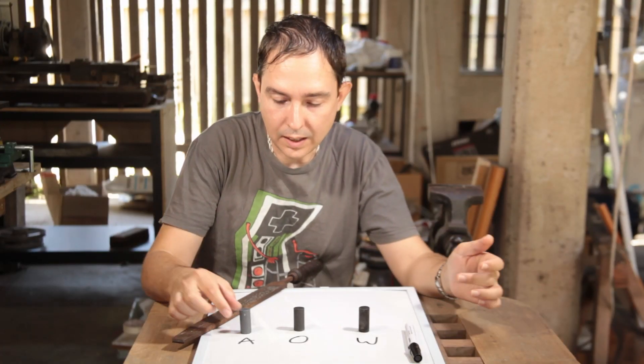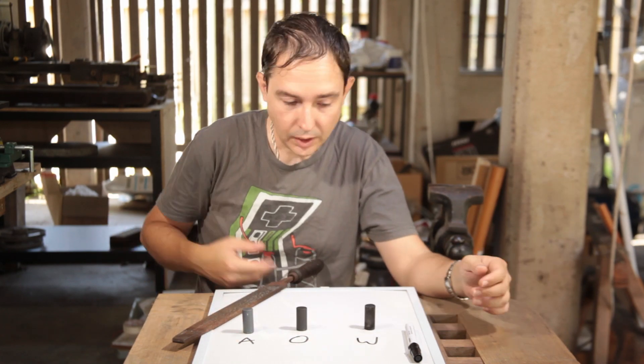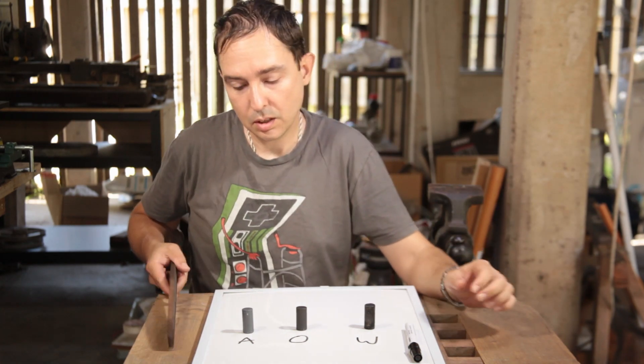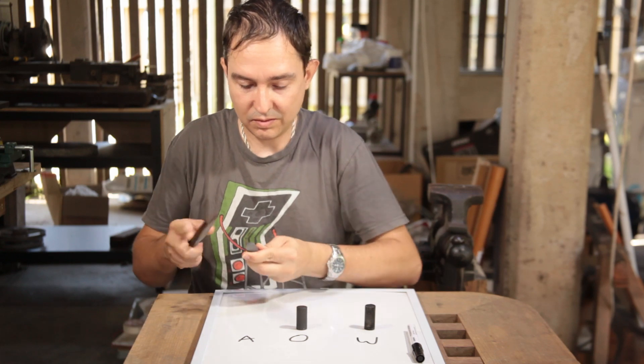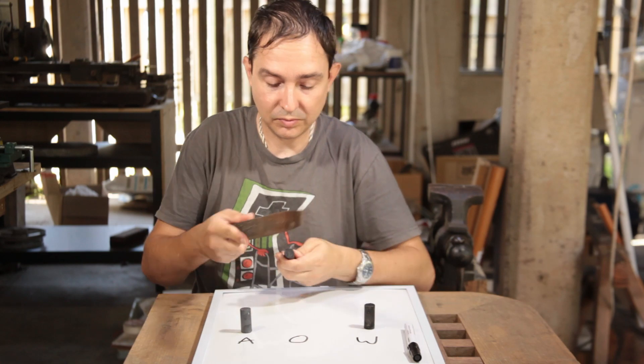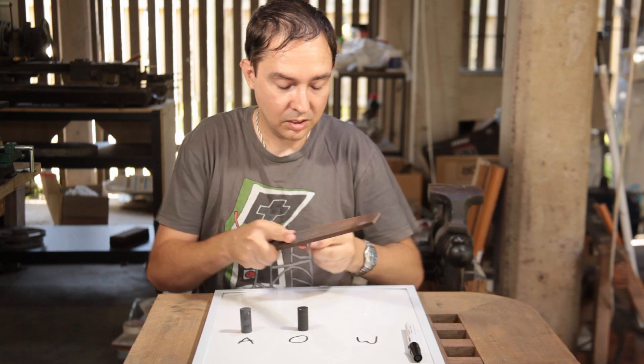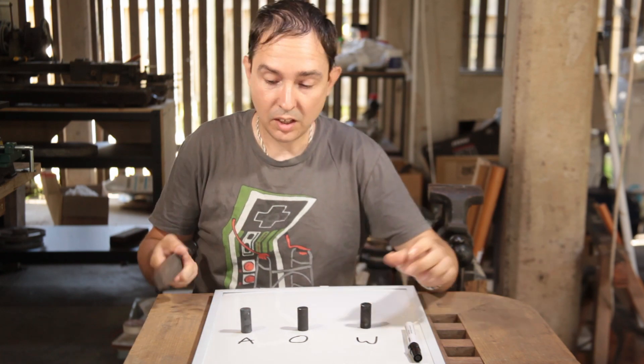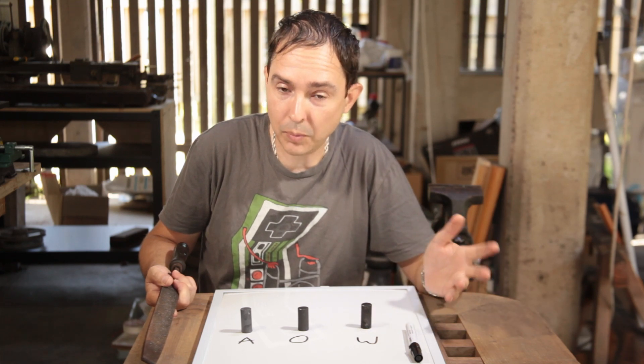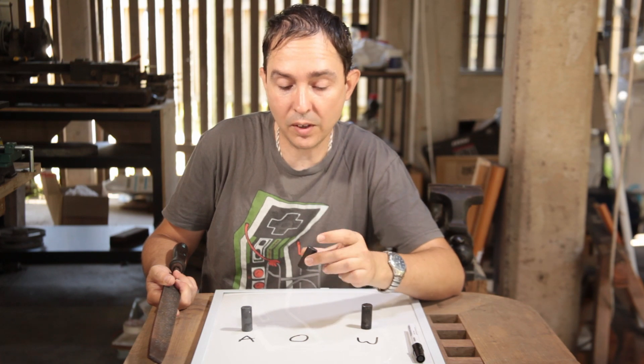So how did they harden? This is the air-cooled one, oil, and water. They're all heated to just on critical. So let's see what happens. Air bites well. Oil — a tiny little bit, but skates. That totally skates. So I'd say this is a water-hardening steel, but for the purposes of the punch, I might just oil harden because it will leave a tougher end result.